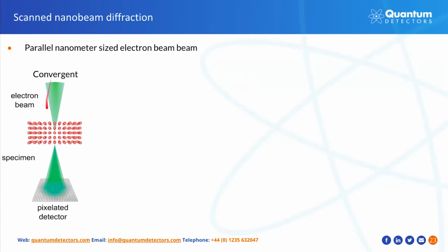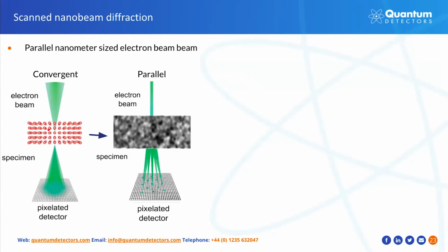Instead of the convergent beam, like we have shown on this schematic, nanobeam diffraction utilizes a small nanometer-sized parallel beam. After the beam is transmitted through the sample, the diffraction pattern in the far field is detected by a pixelated detector. This method is very dose efficient and is capable of collecting information from very, very beam sensitive samples. Once we scan the sample with this probe, 4-dimensional data is again generated.